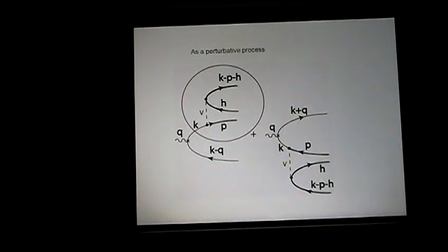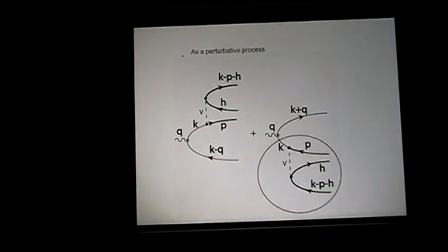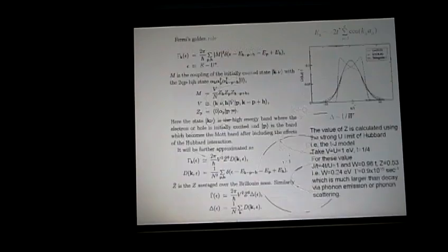It could be that, or it could be because the highly excited electronic state in this other band can decay into 2 quasi-particles and 1 hole state, or if the hole is highly energetic, it can die into 2 quasi-holes and 1 quasi-electron. You can do it for this kind of decay, this death process. You can do, if you like, a back of the envelope calculation using linear response.